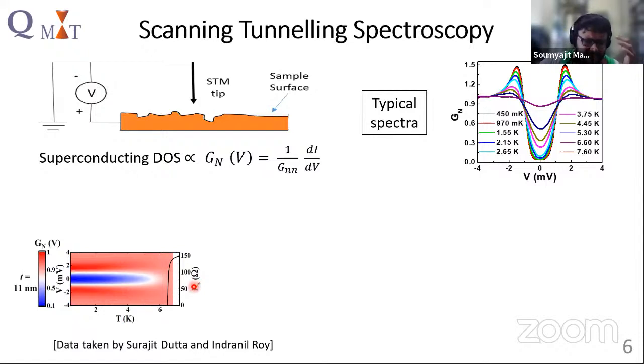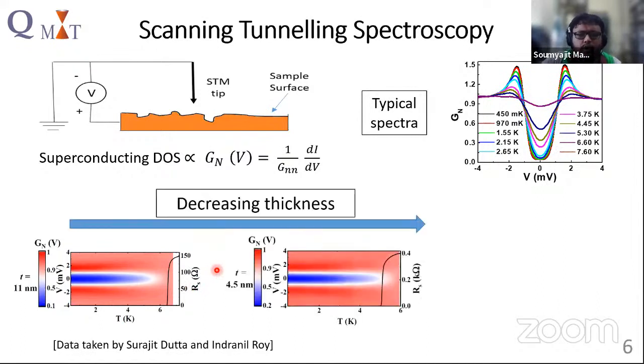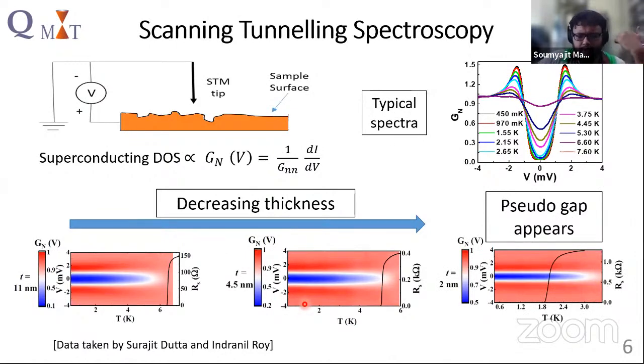So it is expected for the conventional superconductor or the low disorder sample, but as we go to lower thickness, we can see that the gap starts to exist above the transition temperature. If you go to the 2 nanometer sample, we can see that the gap exists even above double the transition temperature we got in the resistance. So you can see that this pseudogap starts to appear as we go to the lowest thickness.